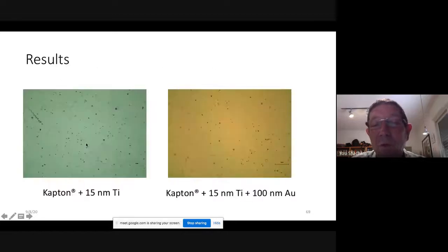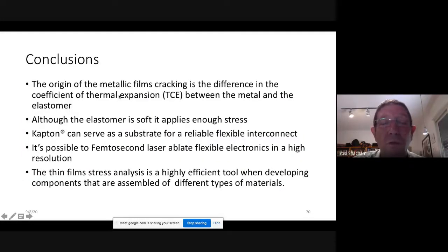So we developed a whole system not only to make electrodes, but to analyze when they break and when they don't break. And we have a table, so everybody that wants to use metal X on a polymer Y, we can predict beforehand if it's going to crack or not. So this is our contribution, that we can forecast for any combination of any metal that we know the properties, if it's going to crack or not to crack. So this is our conclusion.